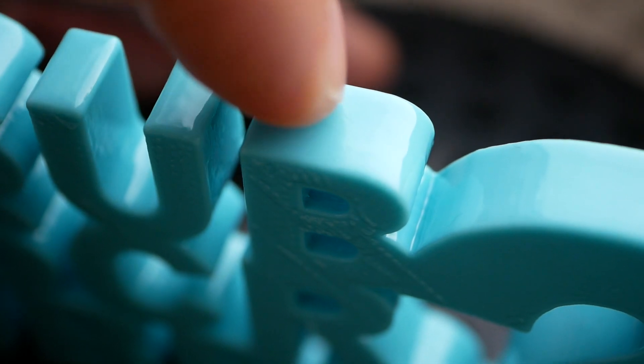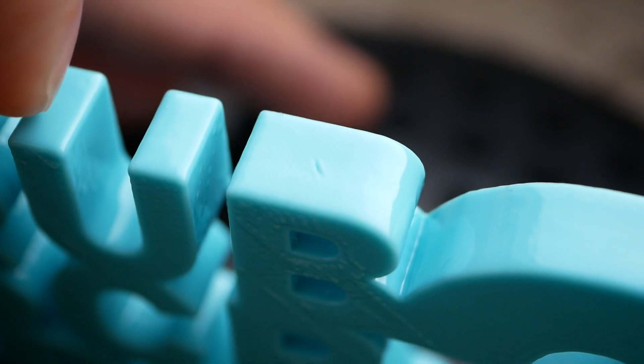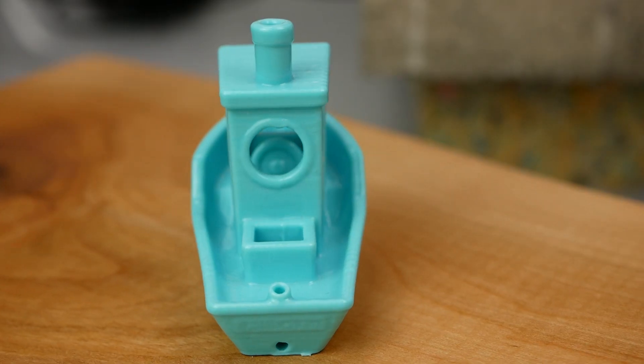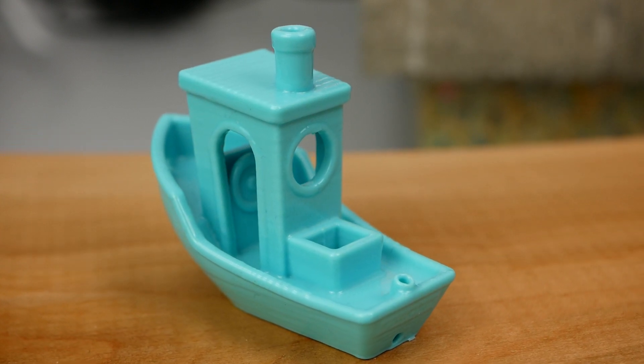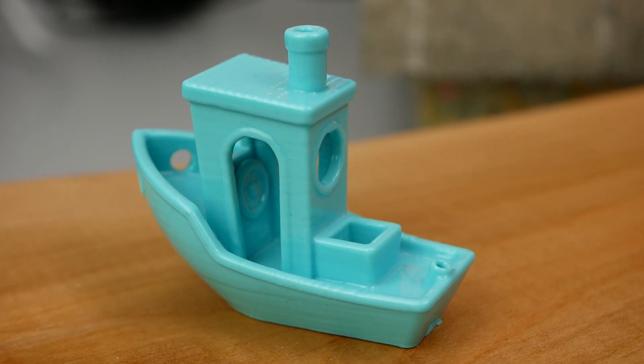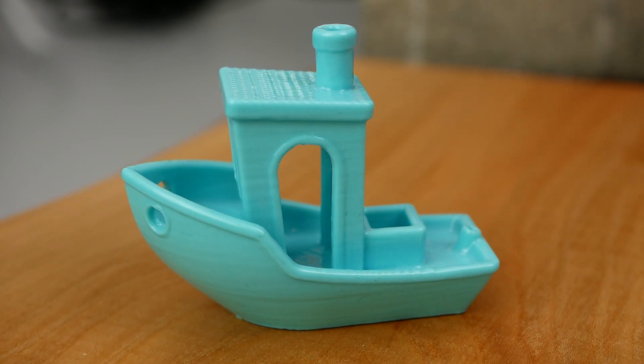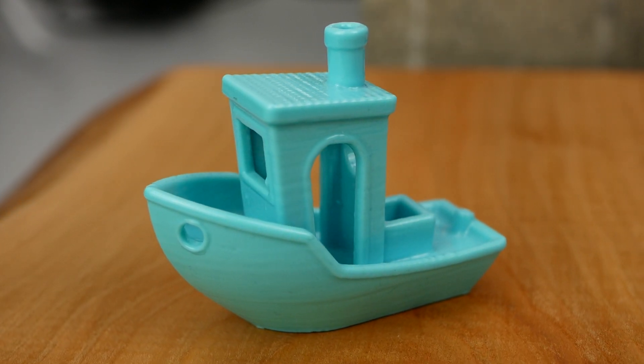Both smoothing techniques leave the parts very sticky and tacky after the procedure until all of the solvent has evaporated from the material. For normal, visually appealing parts, the surface is back to its normal hardness after a good day or so, but since I want it to be totally safe and I'm interested in the mechanical properties, I stored all of the parts for 3 weeks until I tested them.